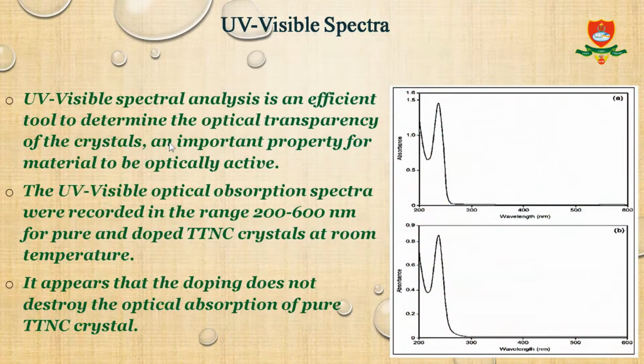UV visible spectra. UV visible spectral analysis is an efficient tool to determine the optical transparency of the crystals, an important property for a material to be optically active. The UV visible optical absorption spectra were recorded in the range 200 to 600 nanometers for pure and doped TTNC crystals at room temperature. It appears that the doping does not destroy the optical absorption of pure TTNC crystal.